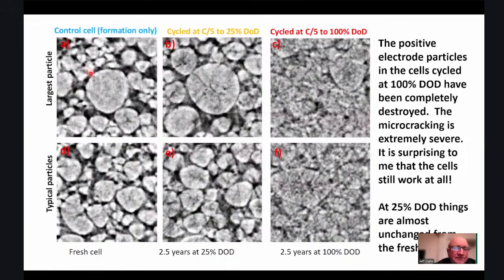So for a cell that's only undergone formation, no cycling, this is what the X-ray computed tomography looks like for the fresh cell. You can see the NMC particles. They look a bit blurry compared to what I showed you with an electron micrograph, but this is inside the cell. And then the cell that was cycled to 25% depth of discharge for 2.5 years, the particles look almost the same as in the control cell.